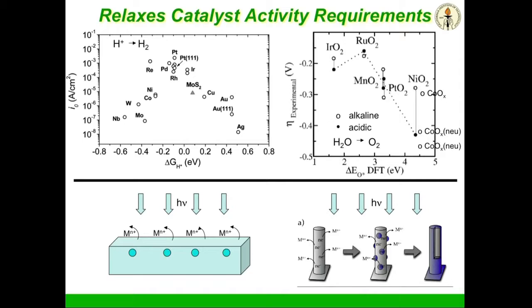On top of that, if we depart from the planar structure, another design principle of these micro rods is they have a high internal area. So the same photon flux now has its charge carrier flux distributed over a much higher internal area. And that means the catalytic requirements are much less, because they have to pass many fewer electrons per unit area than they would if they were all funneled back to the plane. Because our internal area ratio to surface area is another factor of about 100, those 2 factors of 100 open up our ability to use cheap catalysts like nickel and cobalt and molybdenum disulfide and still be kinetically competent, where otherwise only the expensive metals would survive.